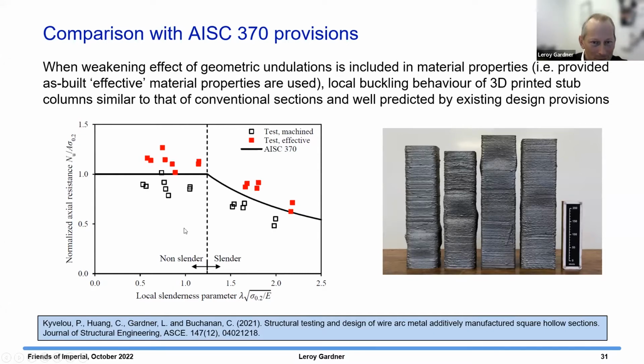And what we found is when we plotted our test results based on the machined material properties, the results are down here, and they lie below the current design curves. So that would be on the unsafe side in terms of a prediction. Whilst if we used the mechanical properties from the as-built coupons, what we refer to as effective mechanical properties, because they have the influence of the surface undulations, we're normalizing by a lower strength, so the points move upwards. And actually, they're now quite well predicted and on the safe side by existing design codes.